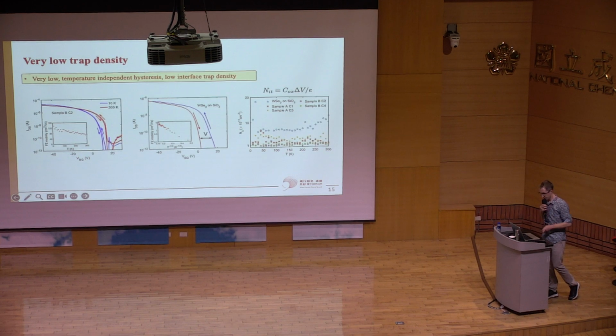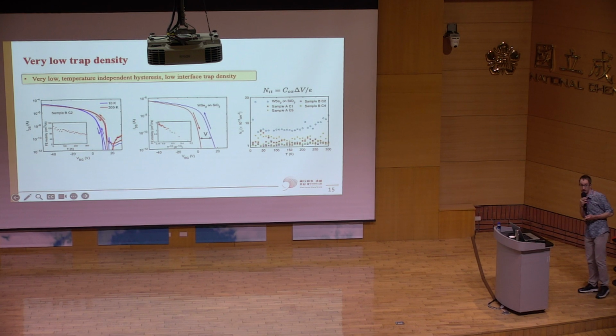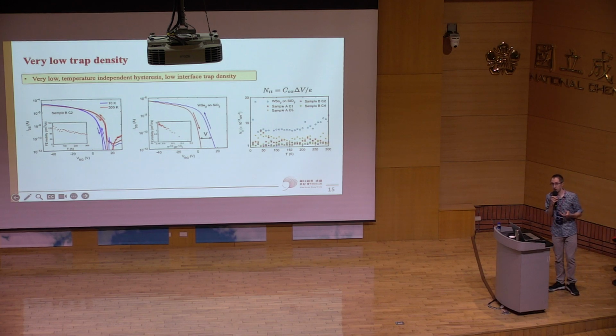Now, the last sort of experimental data I'm going to introduce to you is to do with hysteresis and trap density. So one very special characteristic of these devices is that the hysteresis is very, very low, and it's temperature independent. Now, that's quite remarkable because hysteresis is caused by trap sites, and you'd expect temperature to affect the rate at which those trap sites are filling. So the fact that you don't see much of a difference over such an extreme temperature range is telling you that your trap sites aren't that many.